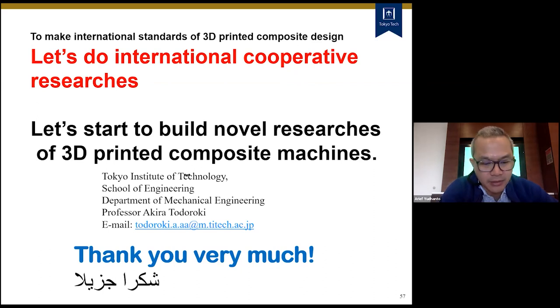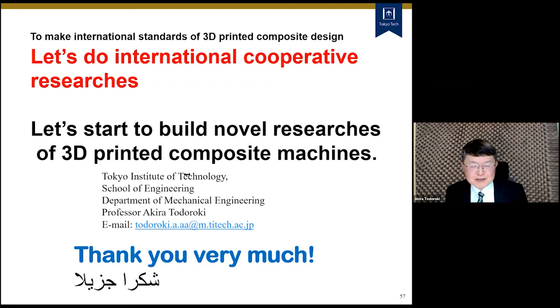But I think Markforged has this facility where you are required to print the outer walls first, at least two layers, and after that you print the actual specimens, right? So by default you need to do it. And the trick that you provided was just to remove it before you do the test, and then maybe you print a different contour of the specimens, right? So we have to use a very tricky way to print specimens without a plastic film, plastic surface.